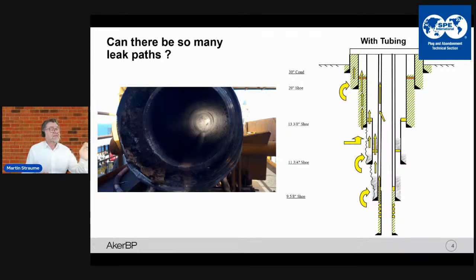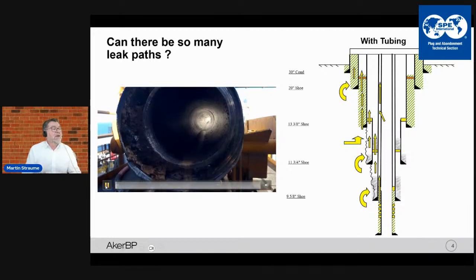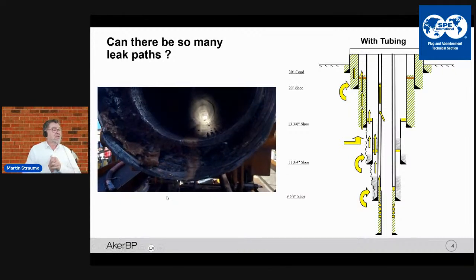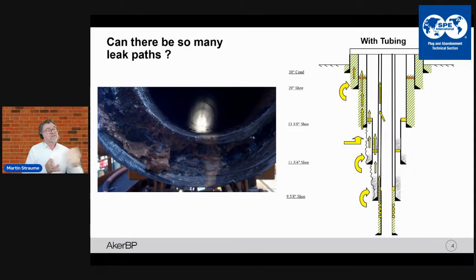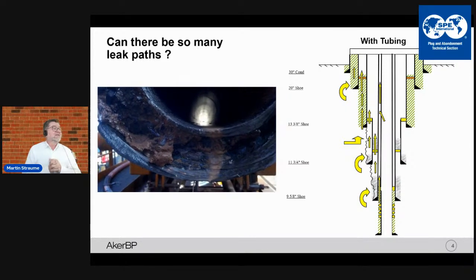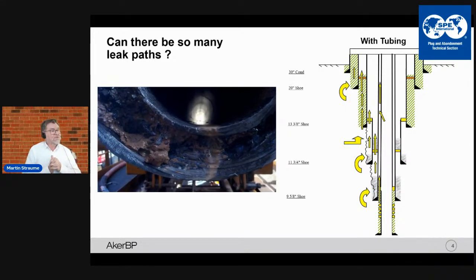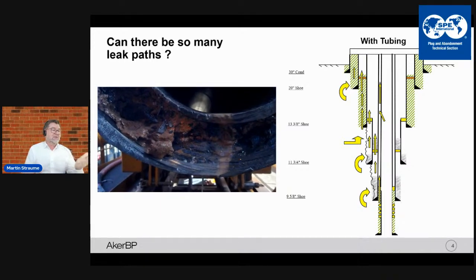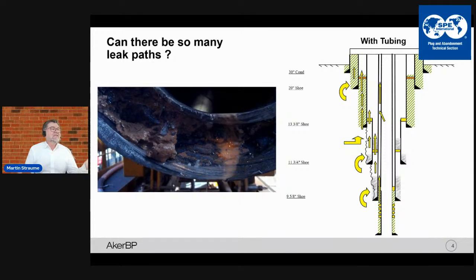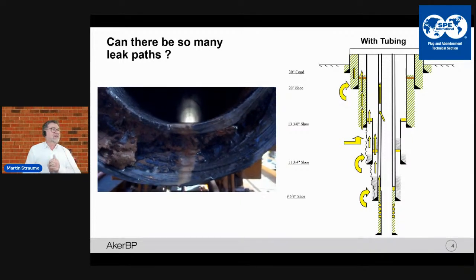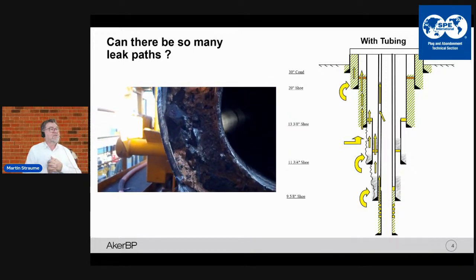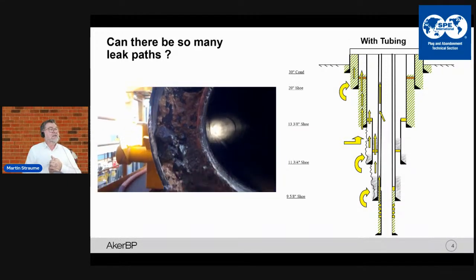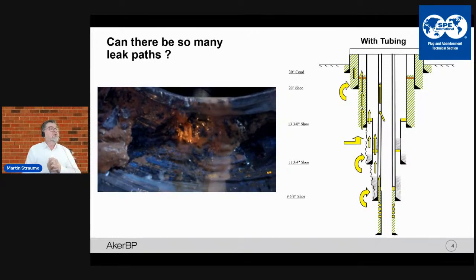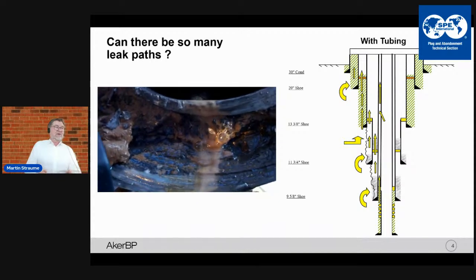What you see here are two casings with annulus cement in between. It's 9 5/8 casing with 13 3/8 casing on the outside. You can see that this was cut and pulled to surface, and you can see how the gas actually empties itself from the pore system in the cement. So cement isn't necessarily sealing all the time. It depends on how it's done and how lucky we are with the cement job. Cracks could occur also, and whether this is caused by cracks or something else, I can only speculate.